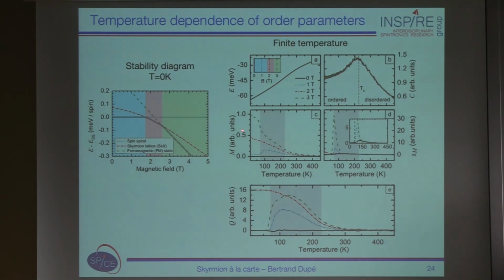Now if you look at the magnetization for the 4 different cases, you see that it's more complicated. You have some features here at low temperature. And if you look at the magnetic susceptibility, you see that you have a sharp peak appearing. So between these 2 bars in this shaded area, there is something going on which we need to analyze. The topological charge gives you somehow a clue: if you increase the temperature and look at the topological charge, you see a sharp increase of the topological charge in this shaded area.